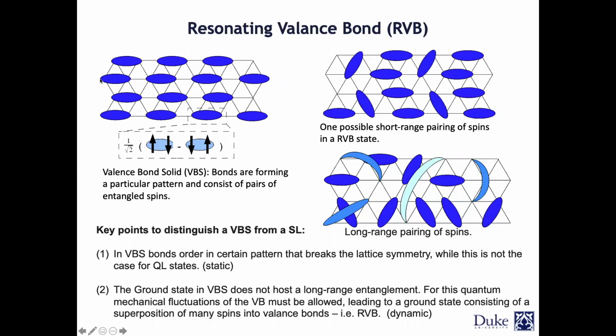And when these bonds are formed, they also introduce some local entanglement. So the pair of spins within each bond are entangled, but locally. Of course, if you have an antiferromagnetic interaction between them, to have a non-magnetic ground state, it is going to form singlets. Now, if we move a little bit further and talk about the resonance valence bond, it is a situation where you don't necessarily have a configured pattern. You can have a pattern, but still, in these cases, the ground state is going to be a little bit more exotic.